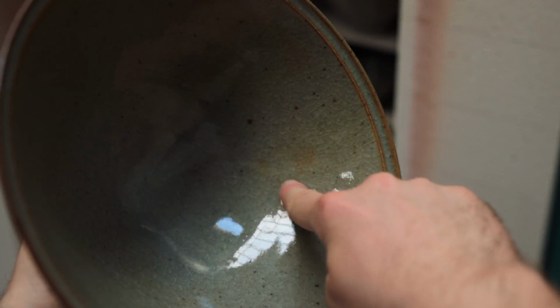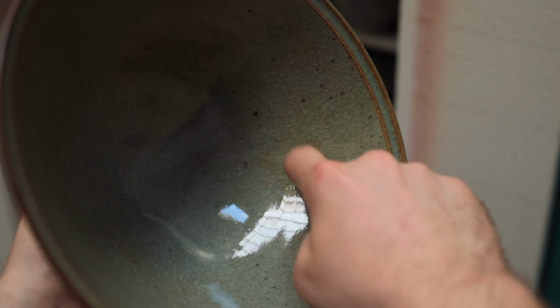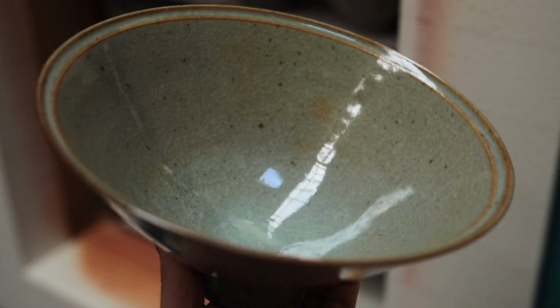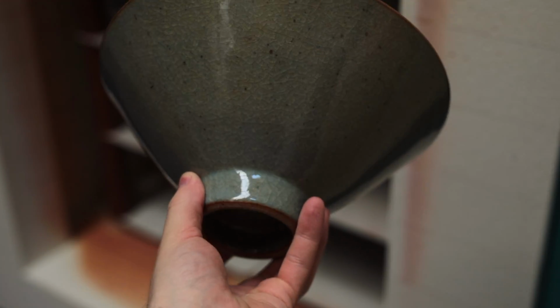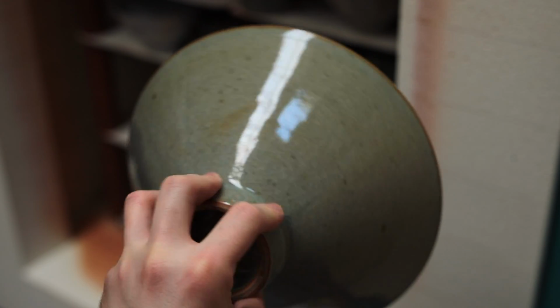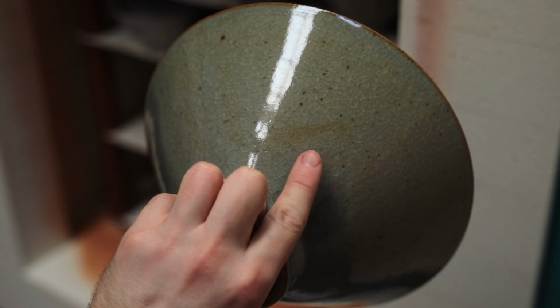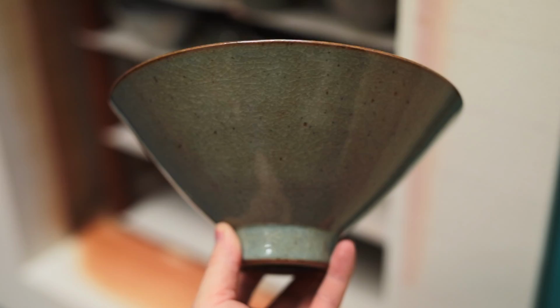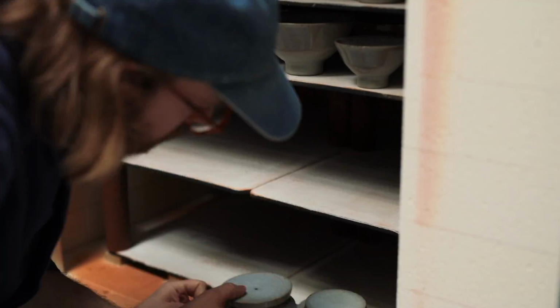At first glance this bowl was lovely, but there's a few patches caused by the glaze being too thin, which most likely is my fault, as I must have fettled it down too much, so I'll have to figure out a way to fix this and re-fire it. At least it's only surface level, so its lovely shape will remain no matter what.